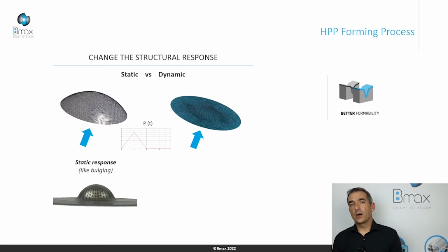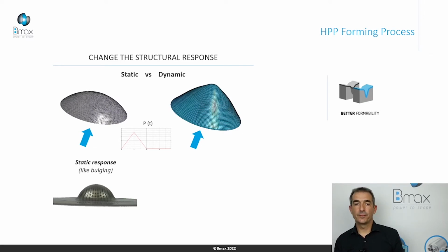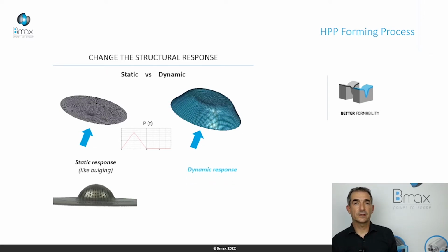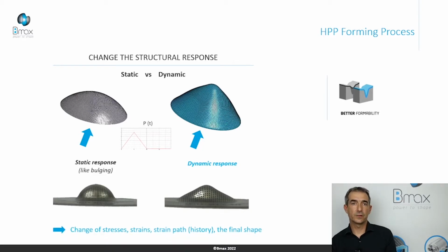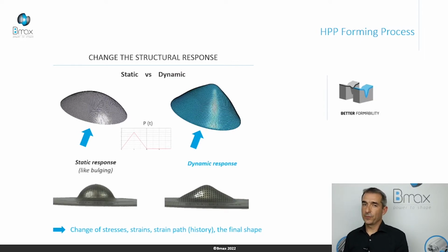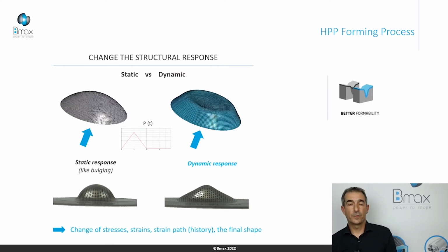If we consider a larger diameter, the stiffness of the structure is reduced, and the most sensitive parameter of the loading is the momentum. We create initial velocity. So the deformed shape of the blank during the process is a flat deformation, constant velocity, and at the end, the final shape is conical. So it's a dynamic structural response of the blank. Thanks to dynamic loading, we can change the stress, the strain, the deformed shape, and in this way, we can enhance the formability.